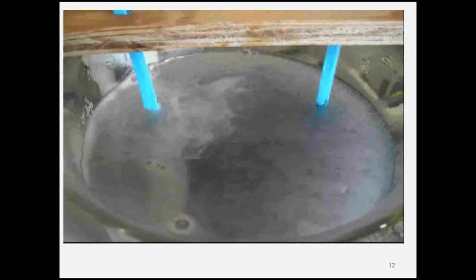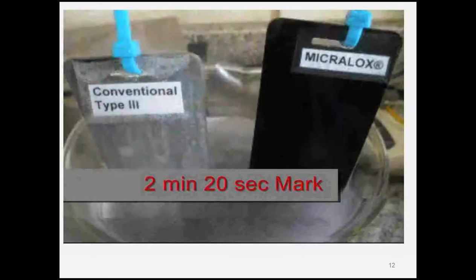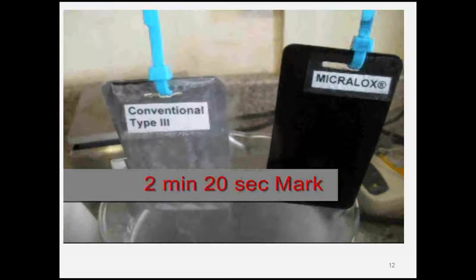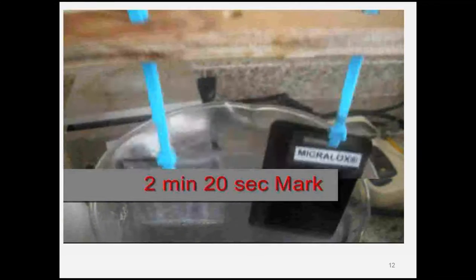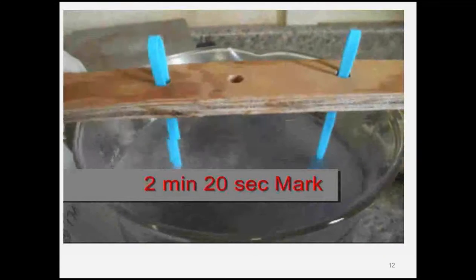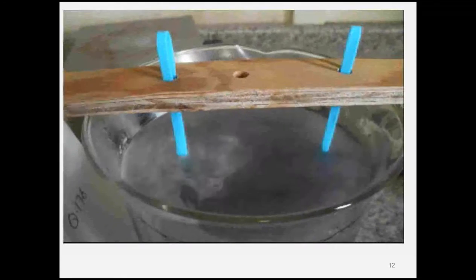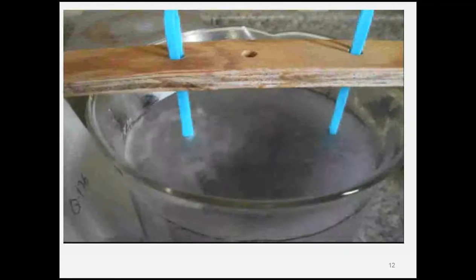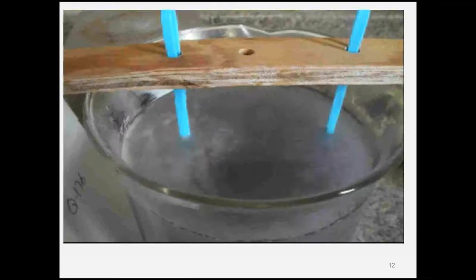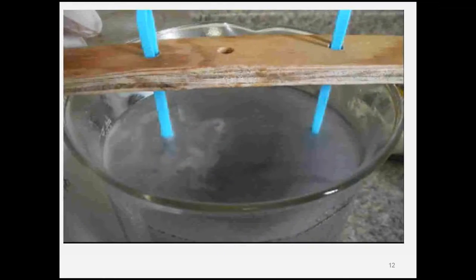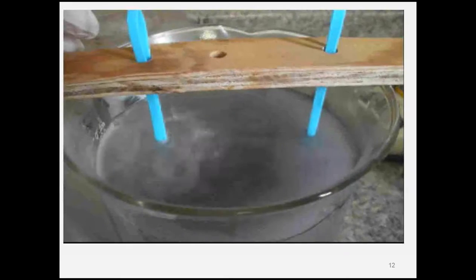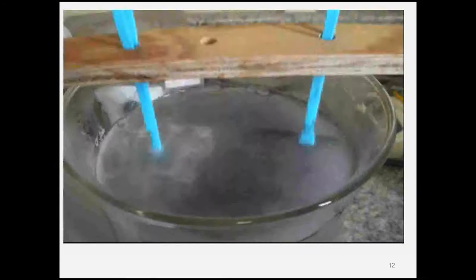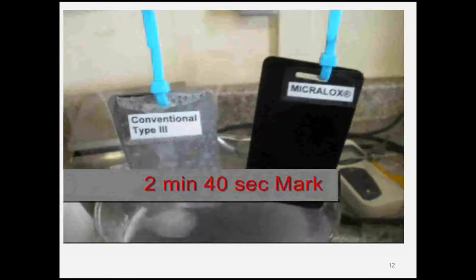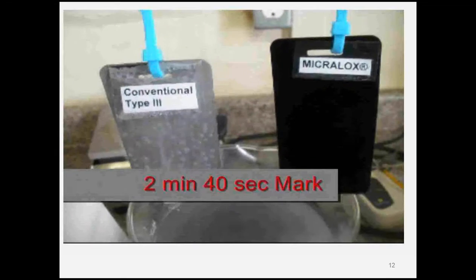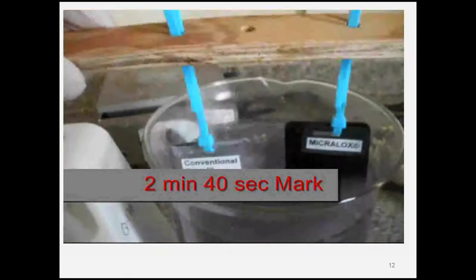Now you can see that the attack on the type 3 is violent. The gassing or outgassing is very aggressive. The coating is now beginning to disappear, not just the black dye, which you now can see floating and swirling on the top. And here it comes out. You can begin to see some actual aluminum color, 2 minutes and 40 seconds.